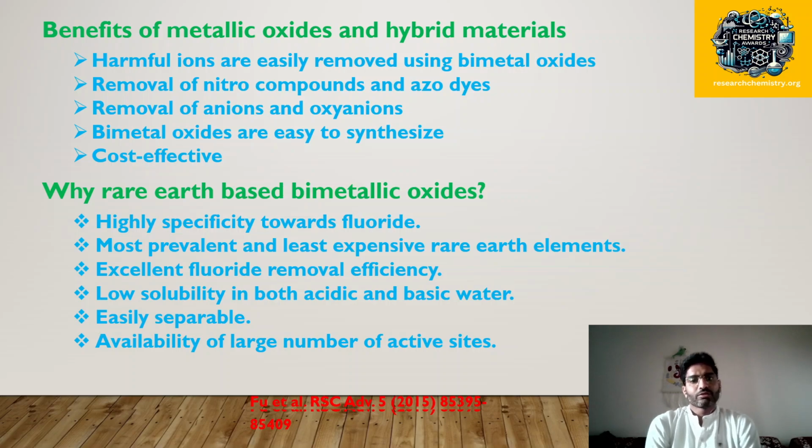And among all those metallic oxides, we prefer to use rare earth-based metallic oxides, as they have high specificity towards fluoride. The most prevalent and less expensive rare metals have been chosen for the successful and efficient removal of fluoride. These have excellent fluoride removal tendency. They have very low solubility both in acidic and basic water, so in both media their solubility is quite low, due to which they are easily separable.